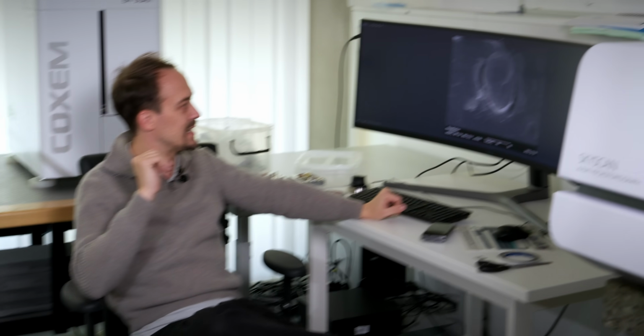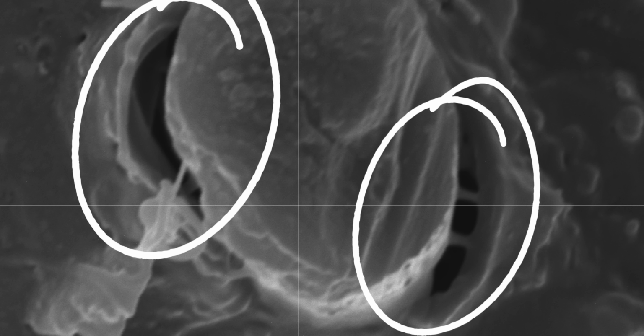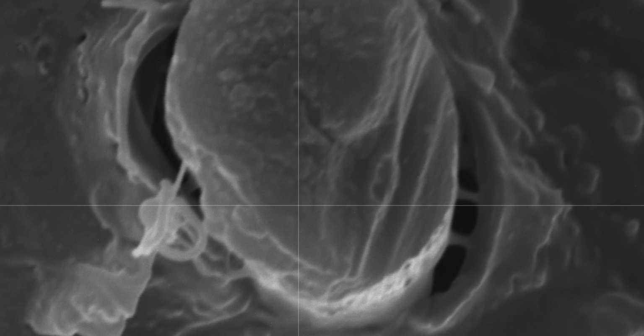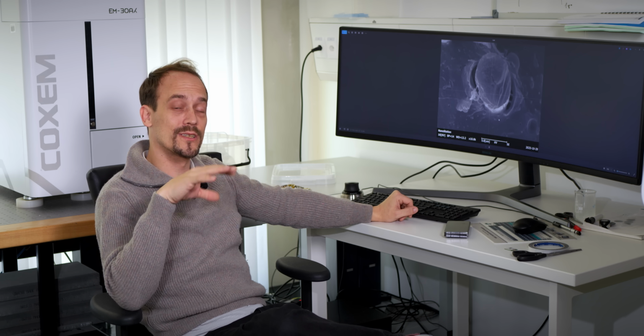So if we zoom in a little more, you can actually now really well see the gaps, the retraction of the polymer from the carbon fiber itself. That means also this manufacturer didn't solve the issue that the carbon fiber has attaching itself to the polymer of PLA. So the wetting problem is still not solved and the fiber was not properly conditioned.